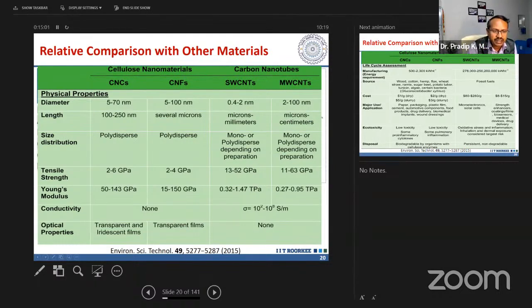Now, if you see the comparison, tensile strength is 2 to 6 GPa for us, whereas for CNT it is 11 to 63 sometimes. The Young's modulus is in TPa, which is very, very high. Conductivity: cellulose nanomaterial is not a conductor. Optical property: it is a transparent film, whereas CNT is not transparent. But from that point of view, you are not supposed to conclude that we should use carbon nanotube rather than cellulose nanocrystal.